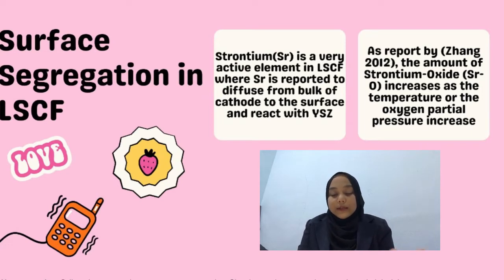The strontium excess in the form of oxide was observed on the surface of the LSCF cathode. As reported by Zhang in 2012, the amount of strontium oxide increases as the temperature or the oxygen partial pressure increases. Surface segregation or kinetic demixing is also related to segregation due to a chemical or electrical potential gradient. Surface segregation or kinetic demixing in LSCF influences oxygen exchange kinetics, electrochemical activity, and also cation diffusion.